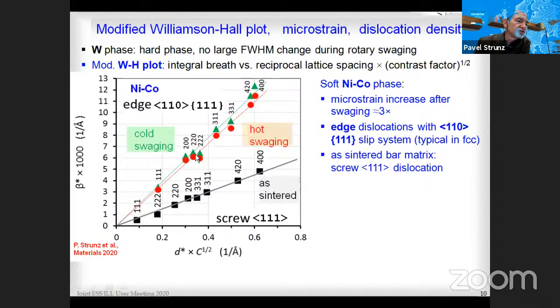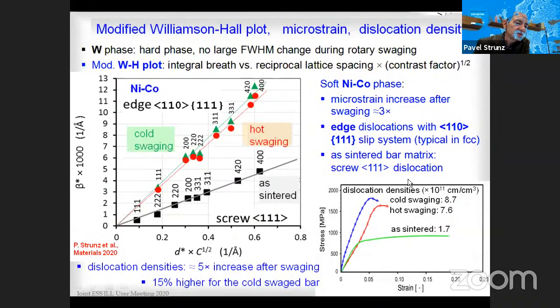And also that the edge dislocation with 110 and 111 slip system fits best the straight line in this modified Williamson-Hall plot, which means that it is the same result as for texture measurement. And there is nothing special. This is typical for deformation texture in FCC structures. Interesting is that here in this sintered bar, the best fit we get for screw dislocation with 111 orientation. We were also able to determine dislocation densities from the measured data. You can see that after swaging, the dislocation density is increased about five times.